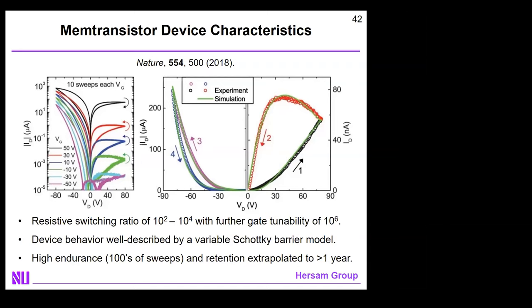We think this polycrystalline MoS2 design is good as a proof of concept. But I do tend to agree with what you're suggesting, that relying upon defects which are randomly distributed in the crystal is going to lead to reliability and ultimately homogeneity issues if you try to push the device dimensions smaller. So what we instead need to do is intentionally introduce the defects via lithography. And of course, that's what we do in conventional semiconductor devices with doping. So I think that is a viable pathway, and we hope to unveil those results soon.